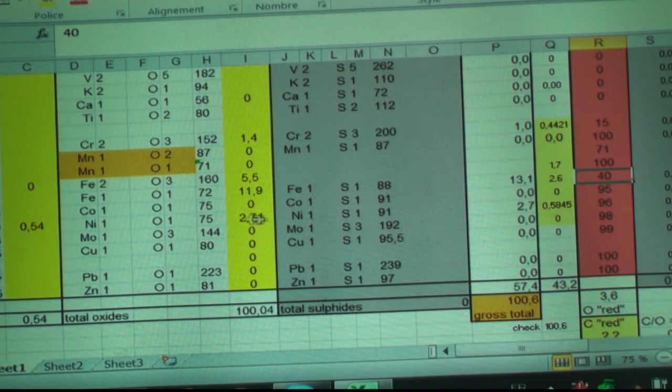You see, the assumption that I made of having NiO is not bad because there is only very little nickel. But on the other hand, they still have some Fe2O3, while I had assumed that everything was FeO. But I cannot decide and you cannot decide, because this is the input of the calculation. The customer has to give you this.